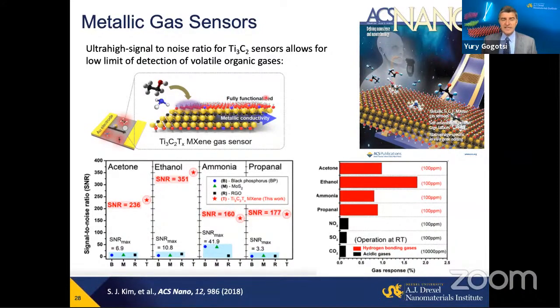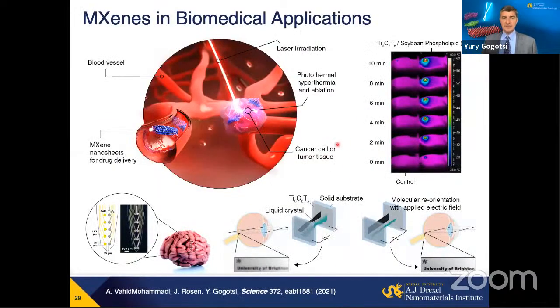And MXenes can intercalate or adsorb on the surface, due to surface charge, many molecules like acetone, ethanol, ammonia, and others, especially positively charged or polar molecules here. And their conductivity changes of the film where this happens. But because they're metallic, because they're highly conducting, there is a very low noise level. And you don't need to heat it up to 200 degrees C, for example, compared to many oxide sensors. So they appear to be attractive in this gas sensing application here. Again, based on their conductivity, change of conductivity that we know after adsorption, intercalation, and their metallicity here.